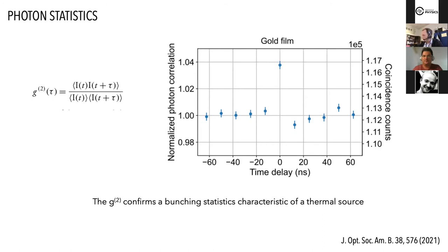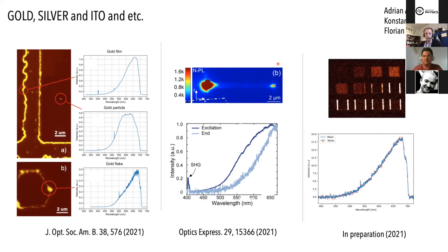The other thing I wanted to show you is that this nonlinear photoluminescence has been heavily reported in the literature for gold, but this is something way more generic than gold. This also strengthens the fact that this nonlinearity is not coming from a particularity of the band structure of gold through multi-photon absorption, but is just related to the electron gas at elevated temperature. And you can bring many structures.